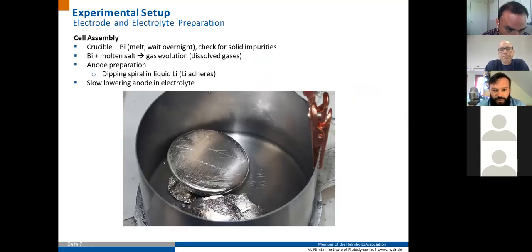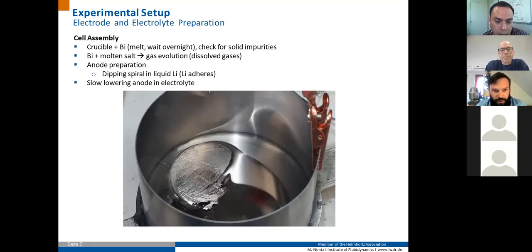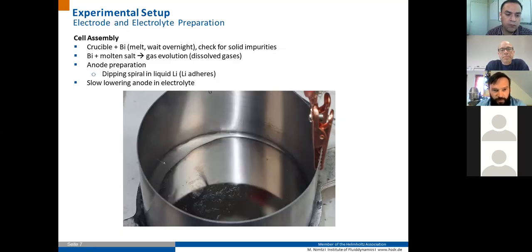Here I'd like to show you how a typical cell assembly will happen. Here it's a larger diameter crucible, around 90 millimeter tantalum crucible, and I'd like to show just some pictures of how typically a liquid metal cell is prepared. First, here you can see a tablet of solid bismuth. This is molten, and typically, if it's fully molten, we wait for a day overnight and check for impurities. As you can see here on the metallic surface, you can already see some impurities, oxides occurring, which then should be tried to be scratched from the surface.